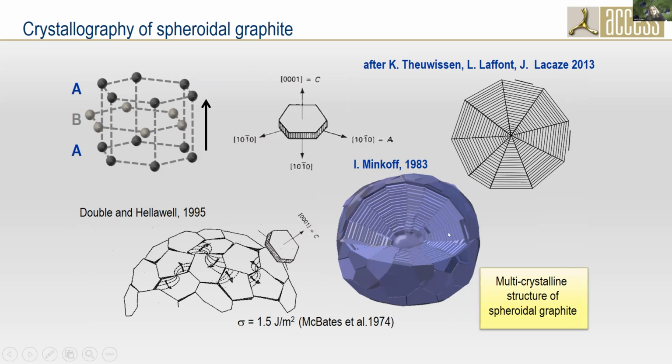And here we have a rather pragmatic approach again. So again, we have a hexagonal structure, but now we have in the basal plane very strong bindings, while we have very weak bindings in the other direction. And this means we can see many different growth forms of the graphite.